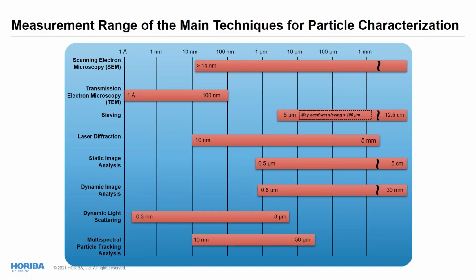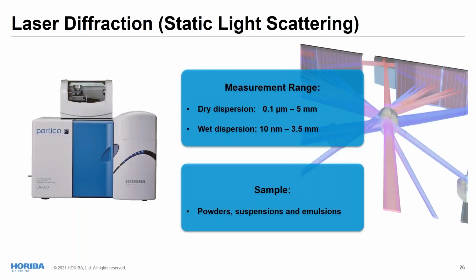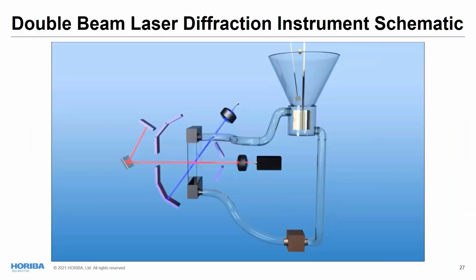So the technique that we're going to talk about today is laser diffraction, because this is the one that ISO recommends for additive manufactured powder. And it has a huge measurement range. It goes from 10 nanometers up to 5 millimeters. With this technique, you can analyze powders, suspensions, emulsions, some cells, aggregates, proteins. So all kinds of samples you can analyze with laser diffraction.